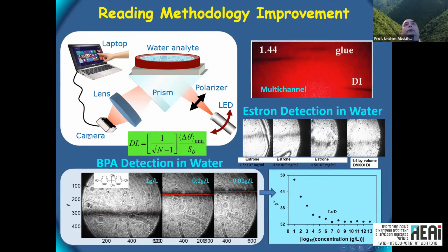If you look at the image, it's not an image actually, it's more like a light distribution. Then you will see at certain angle, you will get a dark line, which corresponds to the resonance for this type of medium. In this case, we have like a channel, and there are two sides of the channel. One side has a water, the channel itself made of a glue, and the other side it has oil. So you see the three of them. The oil has this dark line. The glue also has a darker line. It's not very nice glue, so that's why the contrast is lower. And the DI water has its own line.